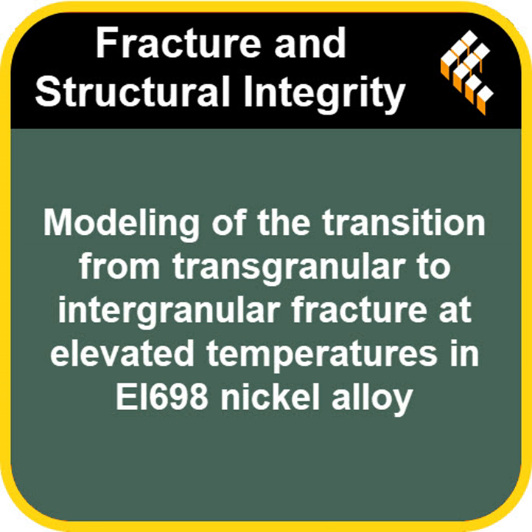And importantly, all of this numerical modeling isn't just theoretical. It's built upon rigorous experimental work. They gather data from a whole suite of standard, ASTM-compliant tests, like uniaxial tension, low cycle fatigue, and creep tests. And these were done across a wide range of temperatures, say from room temp up to 750 degrees C for static loading. These tests are absolutely essential for determining key material properties, like its elastic modulus, how stiff it is, and its elastic limit, basically how much stress it can take before it permanently deforms. We see that in Figure 1 in the paper. And as you'd expect, these properties, like Young's modulus and the elastic limit, definitely change quite a bit with temperature.